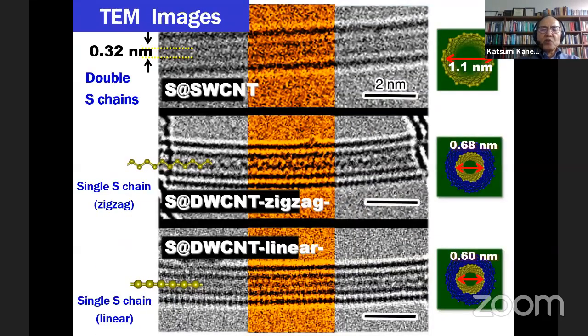In our case, we just evaporate the sulfur in vacuum, and then spontaneously, for example, this is a double-wall carbon nanotube, carbon and carbon. Here you can see the sulfur. This is just a schematic illustration of the sulfur zigzag structure. So the sulfur forms a completely one-dimensional zigzag form, but in a 0.6 nanometer double-wall carbon nanotube, almost a straight sulfur chain is observed. And we can also observe a considerably nice TEM image. We can see sulfur.